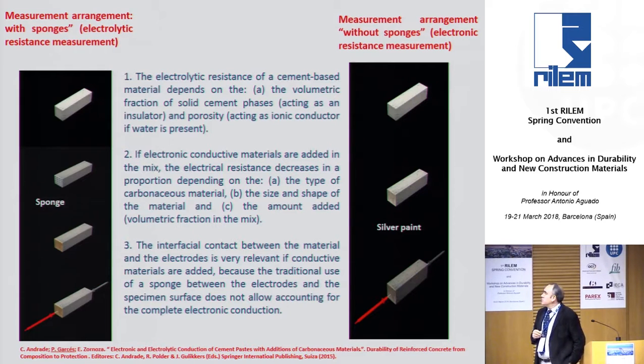In a research work developed in collaboration with Carmen Andrade, here present, titled Electronic and electrolytic conduction of cement paste with addition of carbonaceous materials, the main conclusion, in my opinion, is the first one: the electrolytic resistance of cement-based material depends on the volumetric fraction of solid cement phase acting as an insulator, and porosity acting as an ionic conductor, that is, water presence, of course. The second one is the electronic conductive material added, such as carbon fibers.